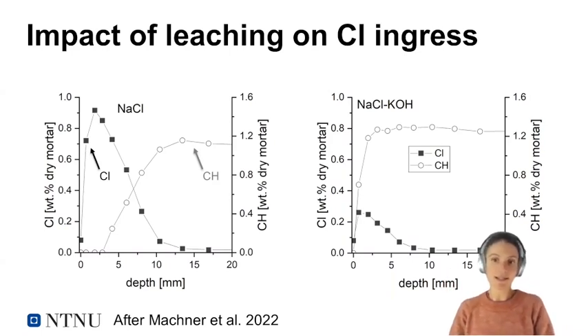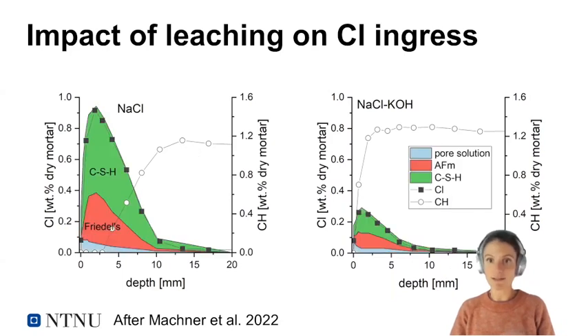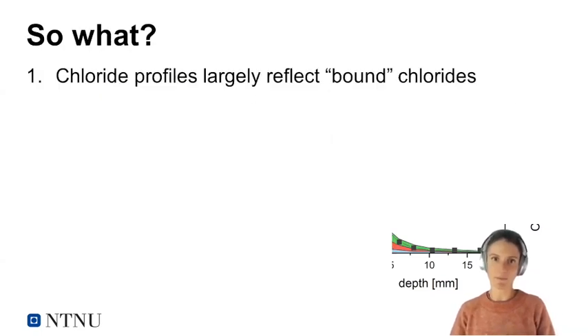And then Alisa linked these chloride profiles to the amount of phases which are able to interact with chlorides and their chloride content. And we were able to match these differences in the chloride profiles by how much chloride is absorbed in the CSH, how much is taken up by the Friedel salt, and also a small portion in the pore solution. So here we really demonstrated how important leaching is when it comes to chloride ingress.